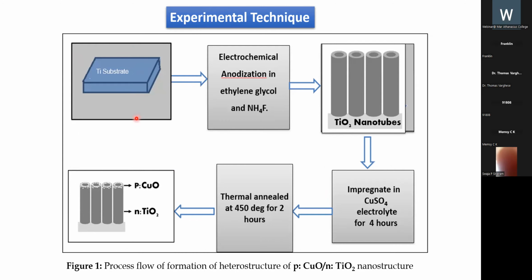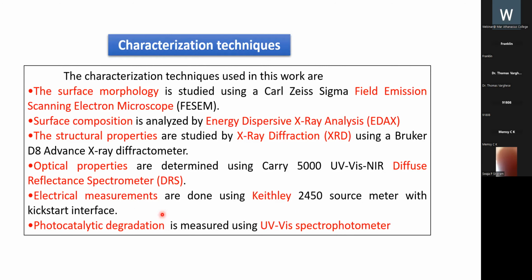Figure 1 shows the process flow of formation of the heterostructure of PCuO and TiO2 nanostructure. Well-ordered TONs are fabricated by anodization of Ti foil in a 2-electrode system with ethylene glycol and ammonium fluoride as the electrolyte at room temperature. These fabricated TONs are then impregnated for 4 hours in a magnetically stirred solution prepared by adding copper sulfate to the aqueous solution of ethanol. The impregnated samples are annealed for 2 hours at 450 degrees Celsius in air to obtain the modified PCuO and TiO2 structure. These are the characterization techniques done.